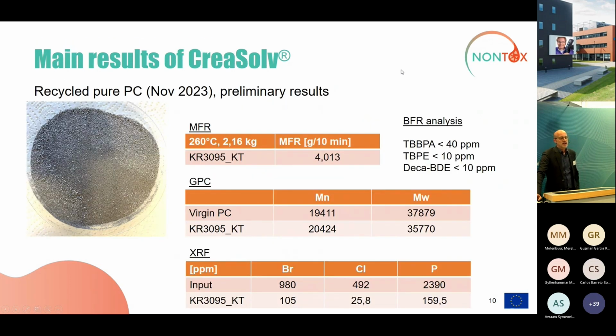And finally, let's go to the polycarbonate fractions. Here I skip the ABS, PC ABS story, since here we had many different results. And some of the drawbacks of these results were just related to having not a clear mixture of PC and ABS. And this is why, in the end, we decided to do the final production in a way that we only produce a purified polycarbonate with the highest value from our perspective right now.